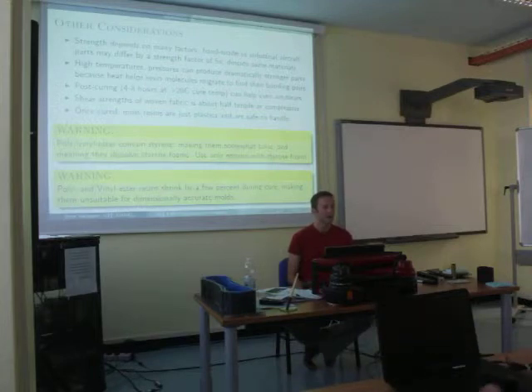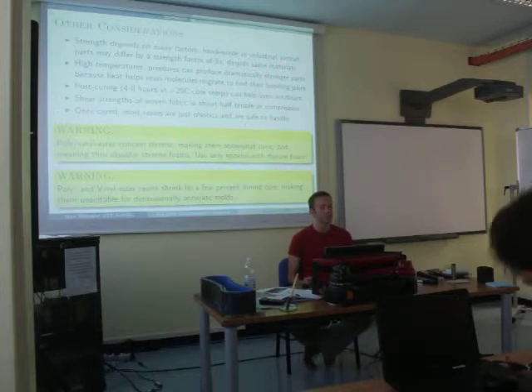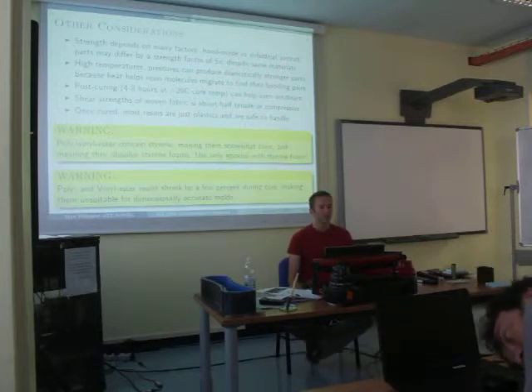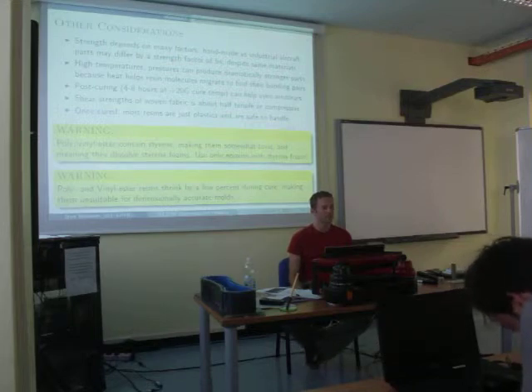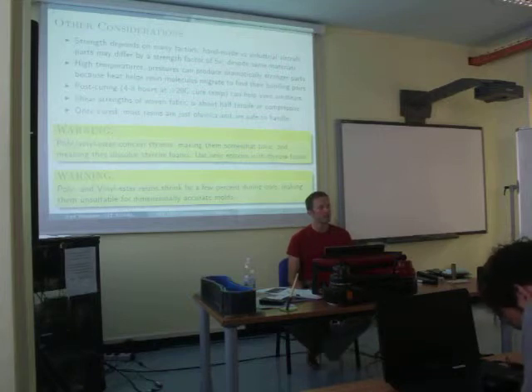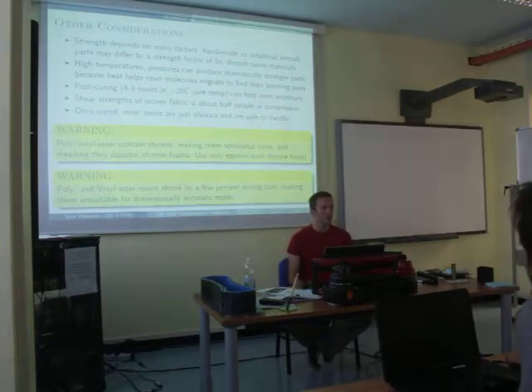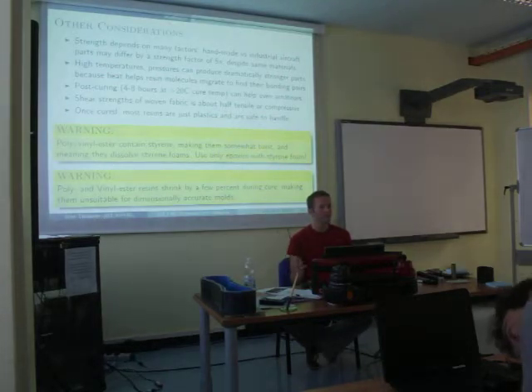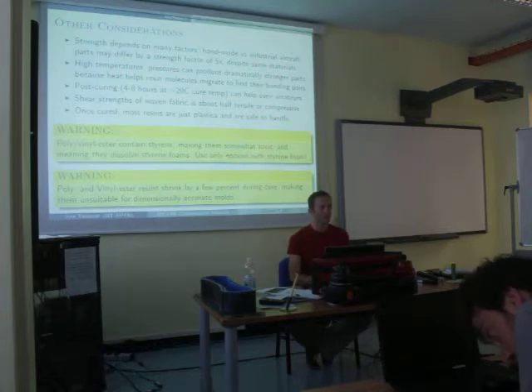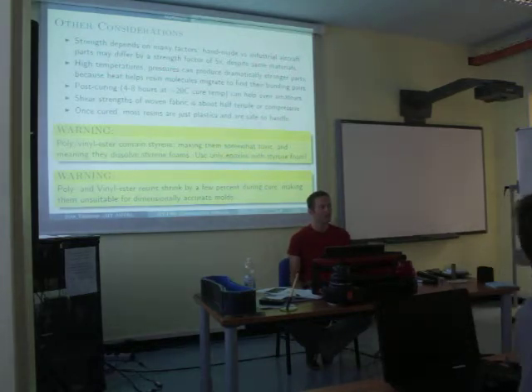Strength depends on many factors. Handmade parts can be about 5 times weaker than an industrially made, properly process-controlled part, even though the materials are essentially exactly the same. One of the reasons this is possible is because professional shops can use high temperatures and high pressures. High pressures can help make a part stronger by reducing the resin content, by squeezing out all that unneeded resin. The high temperatures can help by making sure that all of the epoxy A molecules meet with the epoxy B molecules, and they can find their bonding pairs, so you get a perfect cure of the epoxy resin.